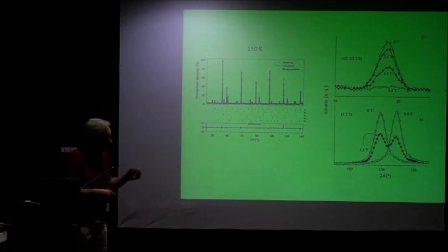So we see from this, it answers the question, is this volume change a continuous volume change, or does one volume appear as soon as the parts become ferromagnetic? And it turns out that the second case is valid here. There is no continuous shift. A continuous shift would mean that as we increase the fields, this would gradually shift to the right.